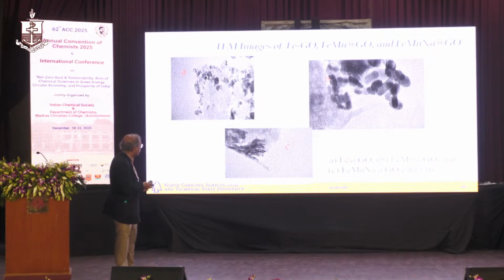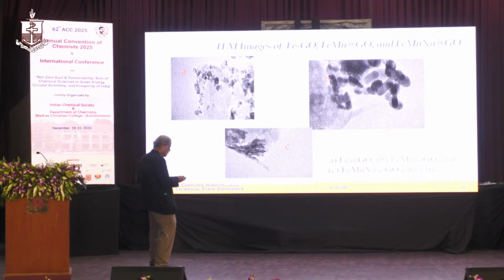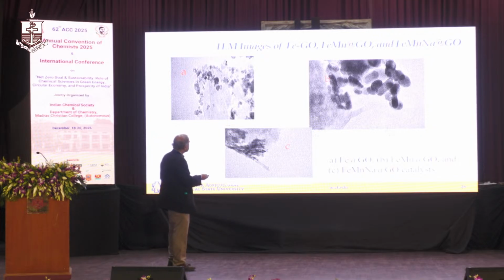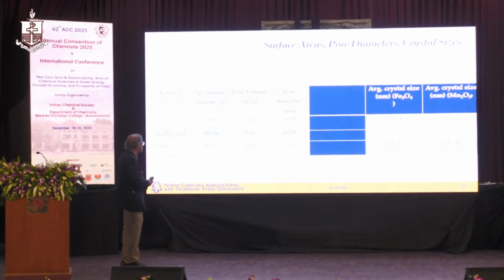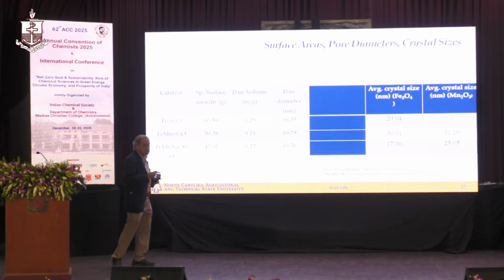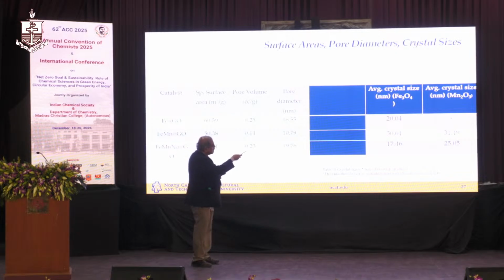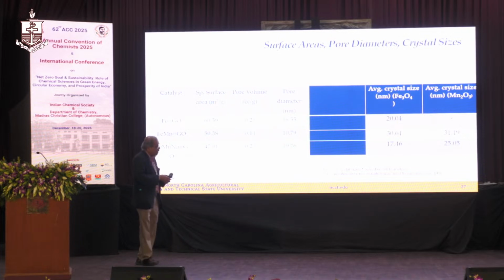So you see that now, this is the manganese and sodium. These are the TEM images, and then you see these are the typical surface areas. Surface area is not that large here, okay? Not like these mesoporous materials. And you can see the average crystal size is like 20 to 30 nanometers, and these are with the promoters. And what you really have is the metal oxide, Fe3O4, or the manganese oxide.